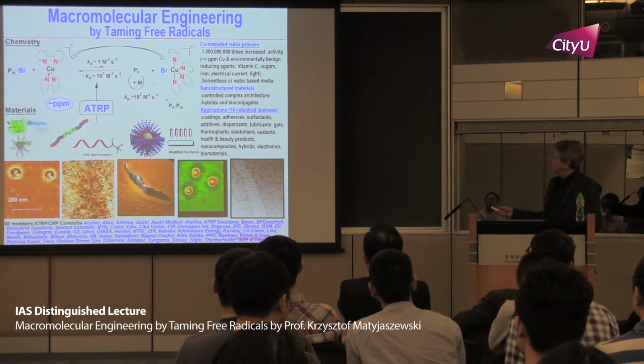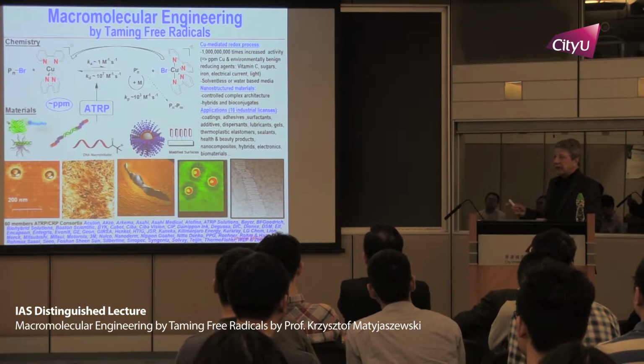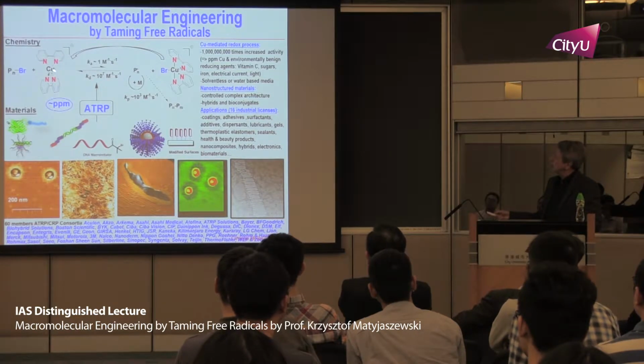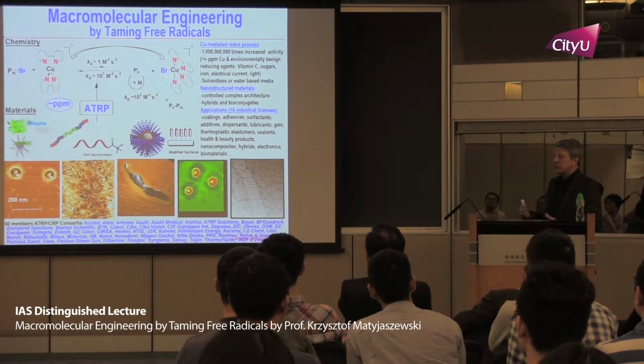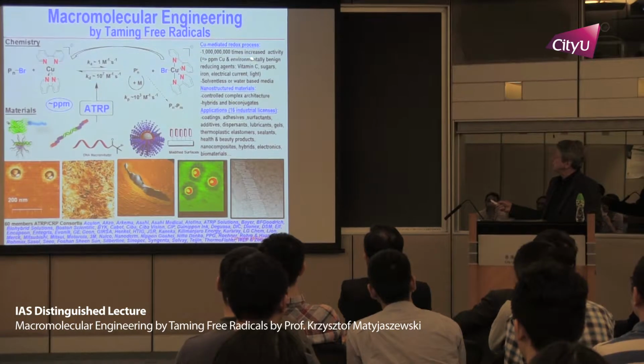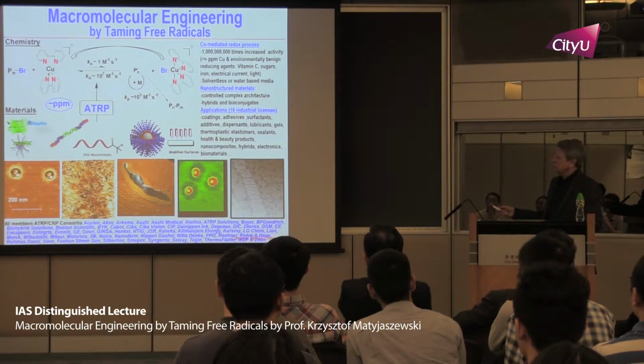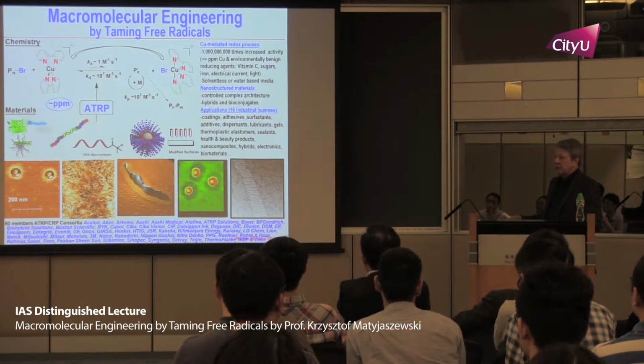So one can use them at very low concentrations, at parts per million. But because radicals always terminate, you will irreversibly convert activator to deactivator, and the reaction would stop. So we need to regenerate this system, and I will show you some examples using very mild reducing agents. You can use something as simple as ascorbic acid, or sometimes sugars, but also external stimuli: you can use electrical current, light, sometimes even ultrasound or mechanical forces.